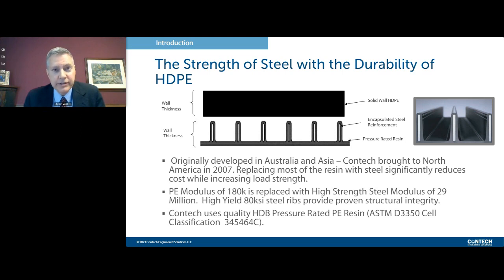And Contech's experience with steel helps us realize that steel is a much better material for handling strength than thermoplastic. And for example, the modulus of elasticity, or Young's modulus of polyethylene, is about 180,000 psi, whereas the modulus of steel is 29 million. And this is not a mild steel. This is a high yield 80 KSI tensile strength steel that's used. And just to put that in perspective, regular corrugated metal pipe typically uses a 35 KSI steel. So it's a very strong, proven material used for the strength in this product.